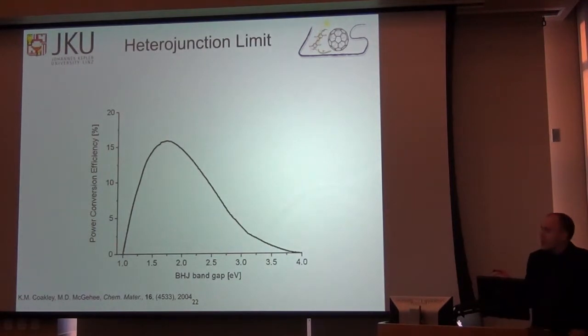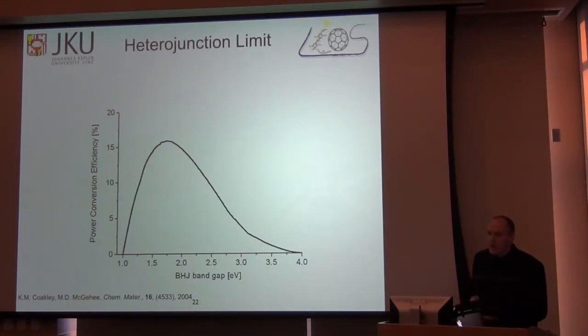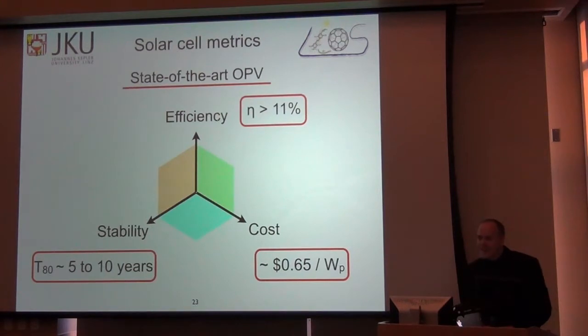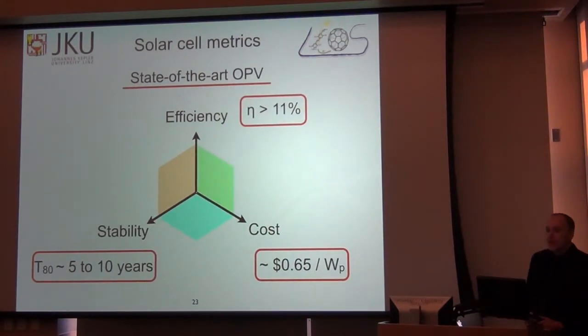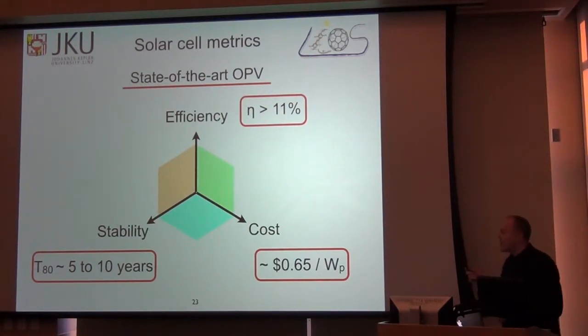That energy offset that I showed before brings our heterojunction efficiency limit down from the 33%, 32%, down to closer to 15%. So here we have some 17%, and this is assuming everything else in the device is exactly perfect. So that energy offset brings us very far below what we would ever hope to get in terms of maximum power conversion efficiency. And so where do we stand now in 2015 with organic solar cells? The efficiency record for an organic solar cell, which uses a polymer and a fullerene, like I showed before, not the same polymer, not the same fullerene, is 11% power conversion efficiency. And that's not too far off from the maximum 15-16% that we might eventually be able to get.